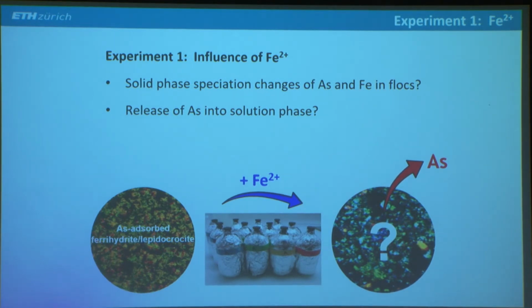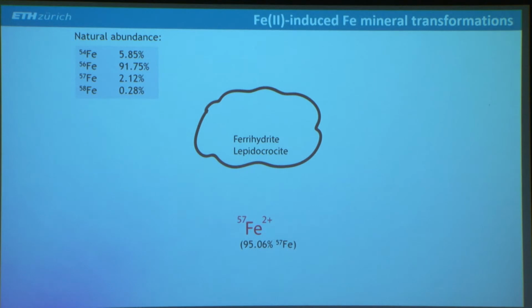So in order to explain a little bit more the concept of this experiment and what might happen, I made a little cartoon here. So this could be the flock sample with ferrihydride and lepidocrocite. We spike iron 2, but in this experiment we used an isotopically enriched iron 57 spike. So this contains 95% iron 57, and the natural abundance of iron 57 is only 2.12%. So natural abundance iron has this isotope composition: the flocks contain 91.7% iron 56 and only 2.1% iron 57.